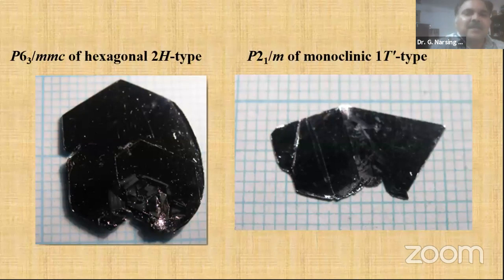Okay, so this type of material, this time we will purify the material. We just seal it inside a quartz tube, melt the material, and collect the end material. So there is a possibility of purifying the material, especially tellurium. These two are different types, but once we solidify this material at the same temperature, we cannot recognize which one is which. So initially we faced a lot of problems.